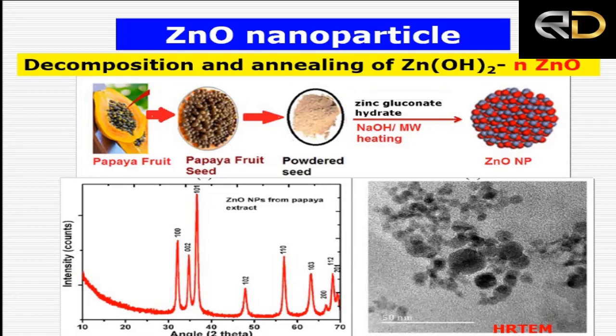One of the simplest methods is to take the papaya fruit, take out the seeds of the fruit, wash it, dry it, grind it, and mix with the zinc gluconate hydrate solution in presence of sodium hydroxide and heat it under microwave. Then immediately you get zinc oxide nanoparticle. These are the transmission electron microscopic picture and the X-ray diffraction pattern of zinc oxide nanoparticle, which confirms that zinc oxide nanoparticle is formed. You can determine the size by using Scherrer formula.